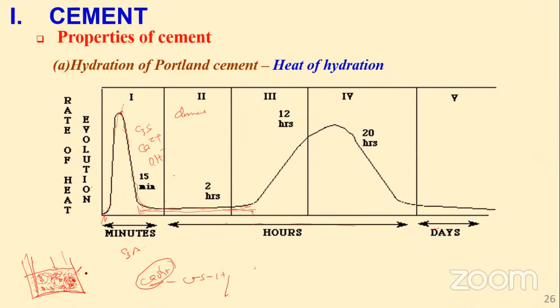What does that mean? The final products that were formed from the reaction fall down. So if we take our container like this, and let's say that was where our content had reached, now we have a residue here of the particles that are falling down, the silicate hydrate. But now we have more free unreacted calcium silicates. Therefore, the reaction speeds up again, and that's why you see the heat going up, up to a point whereby setting starts and then it slows down. But I wanted to explain this stage.